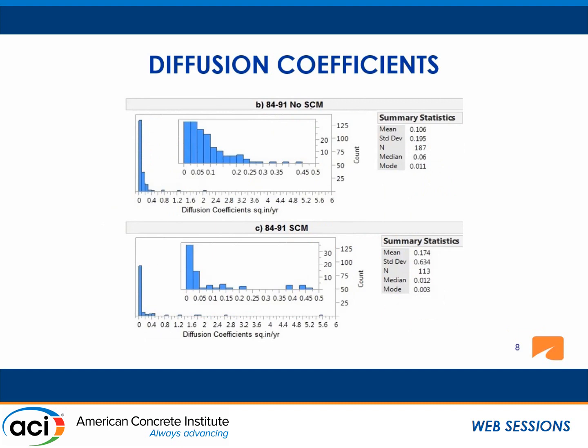And these are the distributions for the diffusion coefficients. As we usually observe, these are some of the most variable factors. And we saw that most of these were concentrated on the lower end, but still we had a really high spread, as we see on the right side.